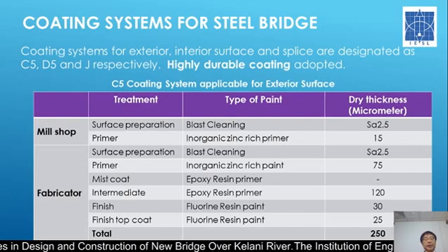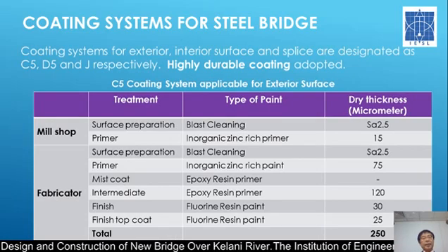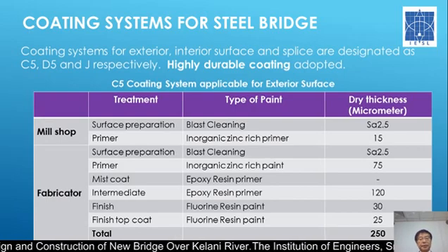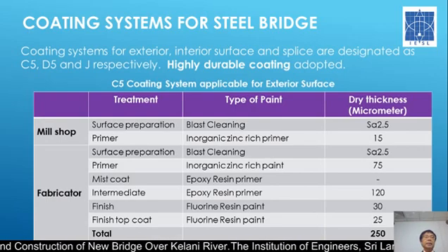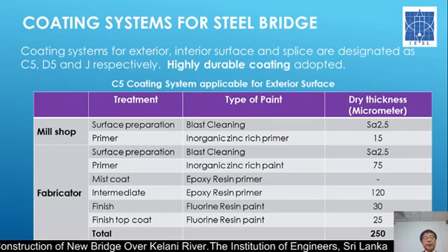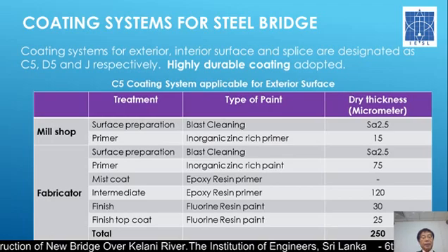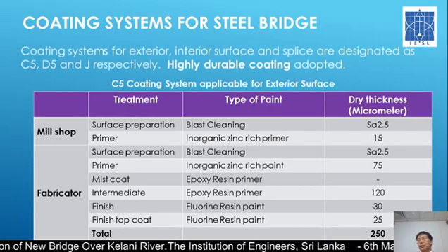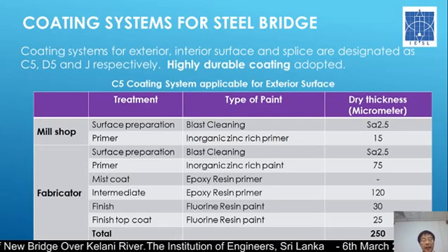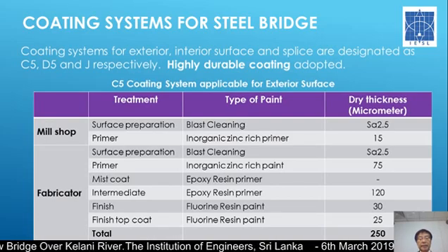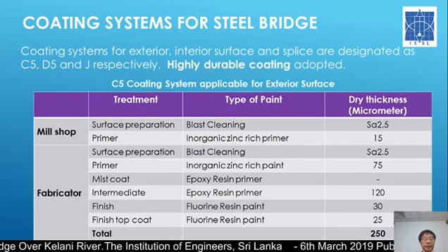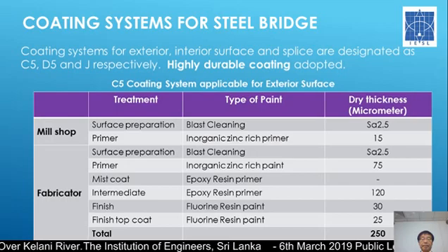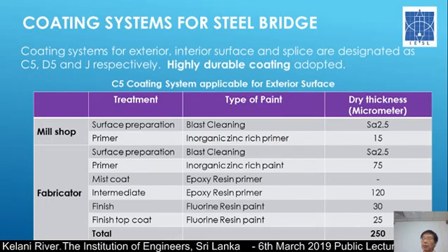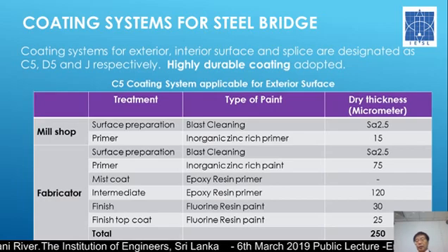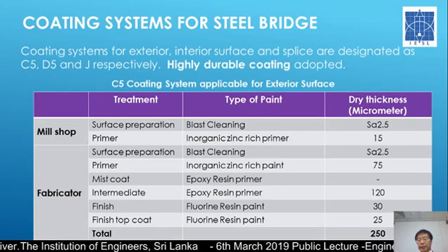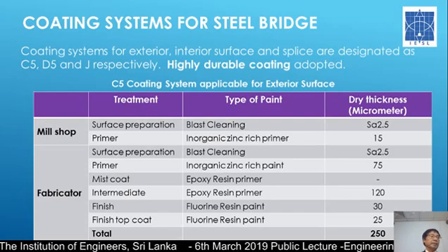Coating: there are coatings used for the exterior, interior, or the joints, and the coating system differs depending on the location. But the most exterior surface, which has to be protected from the weather and atmosphere, uses what we call the C5 coating system, which is also to be used for the first time in this country. At the mill shop, for the plates, they have inorganic zinc primer, and at the fabricator's shop, they apply inorganic zinc paint, epoxy resin, and fluorine resin. The total thickness is 250 micrometers, which is 0.25 millimeters, quite thick.